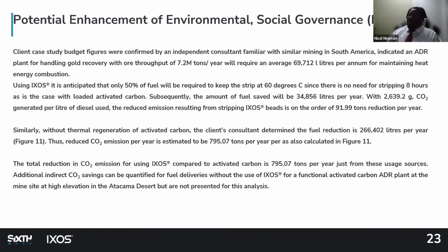Using IXOS, it is anticipated that only 50% of fuel will be required to keep the strip at 60 degrees C, since there is no need for stripping for 8 hours, as is the case with loaded activated carbon. Subsequently, the amount of fuel saved will be about 34,856 liters per year, which is half of what would have been used had he gone for activated carbon. With 2,639.2 grams of carbon dioxide generated per liter of diesel used, the reduced emission resulting from stripping the loaded beads is on the order of 91.99 tons reduction per year.